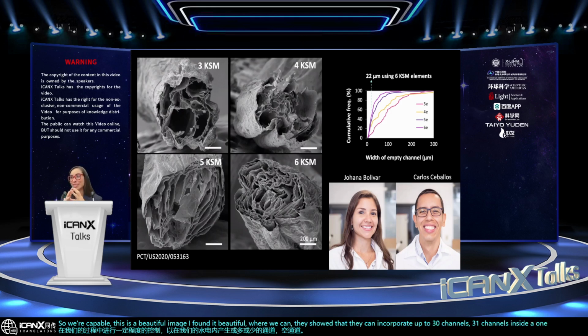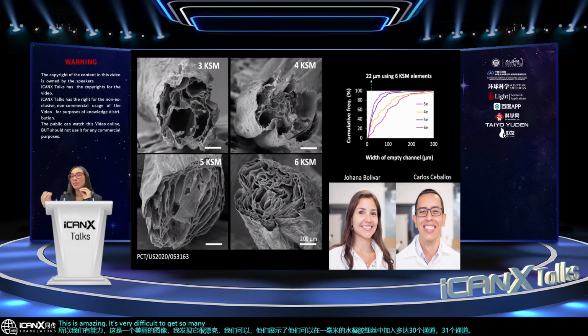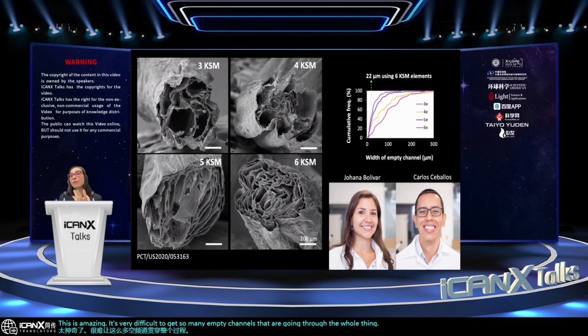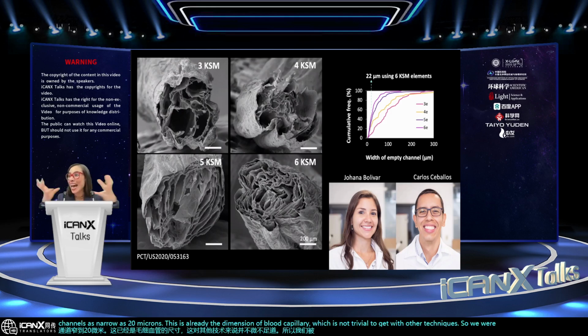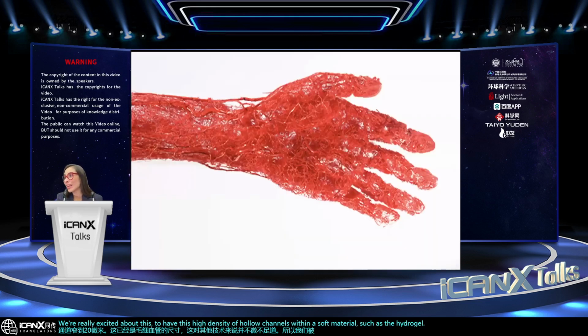So this is amazing. It's very difficult to get so many empty channels that are going through the whole filament of hydrogel. So with this, we were even capable of getting hydrogel channels as narrow as 20 microns. This is already the dimension of a blood capillary, which is not trivial to get with other techniques. So we were really excited about this, to have this high density of hollow channels within a soft material such as a hydrogel, because, well, we need that extent of dense microvascularization in our body if we are expected to make thick hydrogels or tissues in the future.